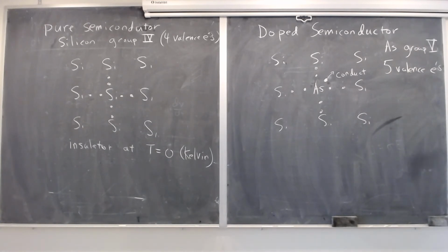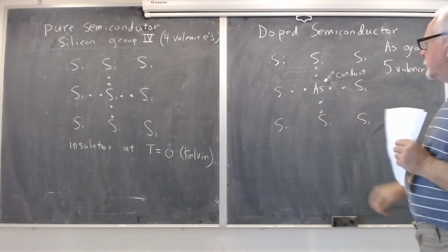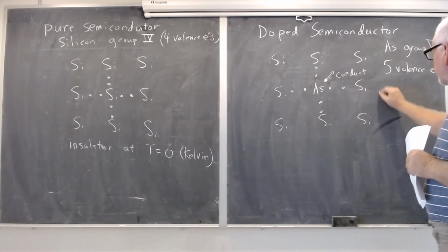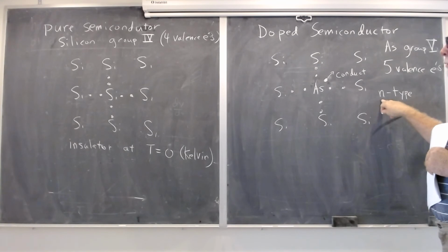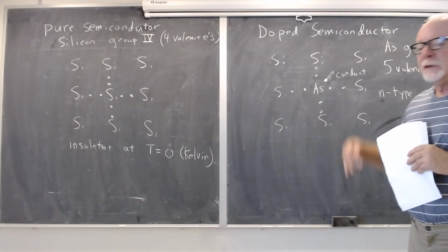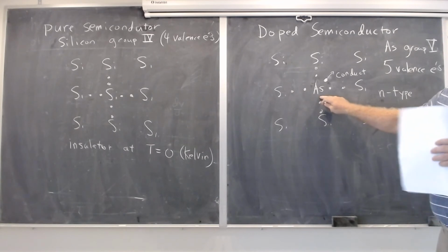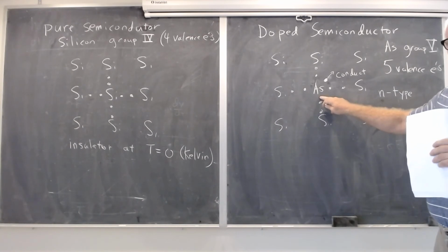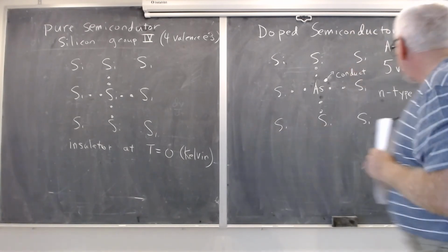Okay, and so the electron can conduct, and since the charge carrier that forms conduction is an electron, it is called n-type, because the charge carrier is negative. And to achieve levels of conductivity required in semiconductor devices, you only have to replace like maybe 1 out of 1,000,000, or at the most 1 out of 1,000 would be very heavy doping of the silicon atoms with arsenic. So that's n-type.